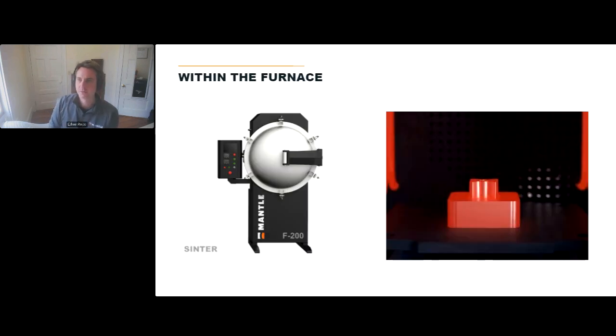After all the printing is complete, we go into a sintering process. If you're familiar with metal injection molding or other powdered metal processes, this is a sinter process. You put a bunch of parts in the furnace at once. It heats up and removes that binder out of the part. It's actually just boiling it out of the part. Then you get up to a temperature where the material is almost at its melting point, and it sinters these powdered metal components together. We do shrink about 9% in this process. That's about half of what you would see in a powdered metal or other sinter-based technologies. But we're able to predict that relatively accurately to achieve plus or minus a thou per inch.